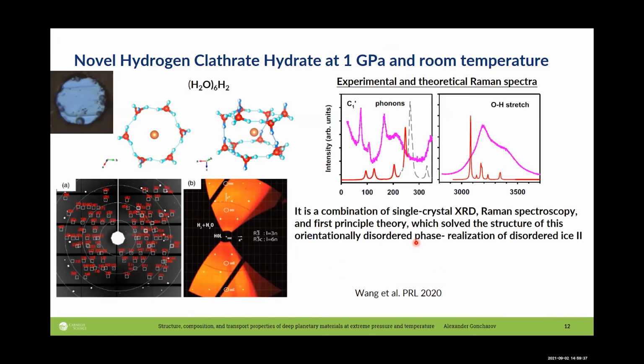Except in certain cases, for example, which I would like to show in the next slide, where we look at the novel hydrogen clathrate hydrate at 1 GPa. At 1 GPa, as you understand, the sample is much larger, so you can do much better experiments and have a much cleaner sample. Here we determined the positions of hydrogen atoms just from single crystal X-ray diffraction, and these results have also been supported by Raman investigation and theoretical calculation.